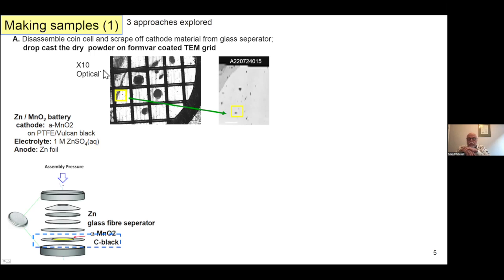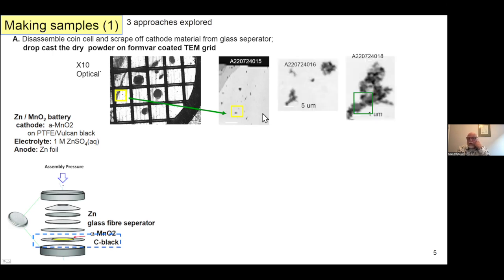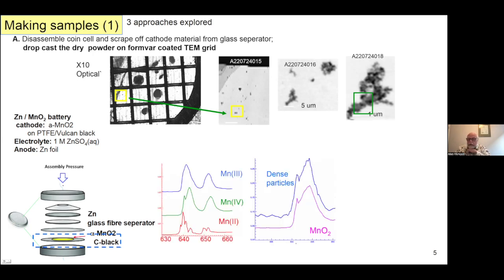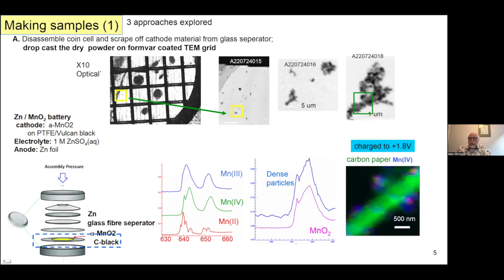In this particular sample, because we had success with preparing simply by scraping the electrodes off a supercapacitor electrode in a previous study, we thought we'd start with that same process. And so here is again an optical microscopy image. In this particular square, you can see there's a fold over of some of the material, but also these little spots. This is now a STXM image. We see the fact that there are spots there, but nothing more. And then as we go in using the higher resolution STXM, we see that there is some morphology there. So that's good. However, when we went into detail to try to map the manganese oxide materials that were present there, we found out that most of that region that was studied in detail in this green box is actually just the carbon material, graphitic material for contact, and it was only these small regions that really contain the manganese.